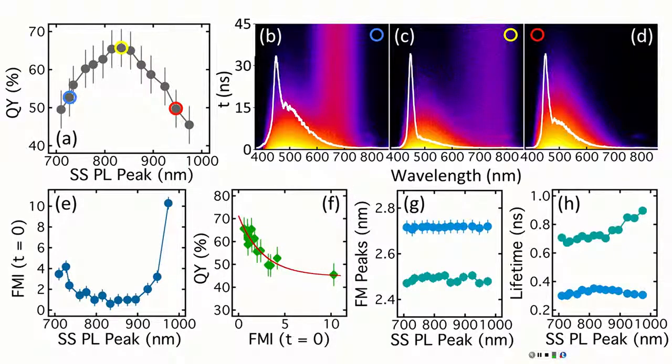No, but I guess you probably say that this mixture with surface states or something like that might be changing the picture, or may help to lift the selection rules. Yeah, because again, you still have a very strong confinement here, so the wave function is spread over the surface anyway, and it feels the surface, it feels confinement, and it feels defects. Your indirect gap should also be coupled to this confinement and surface states, and this changes the selection rules, becoming bright rather than dark, as in bulk.